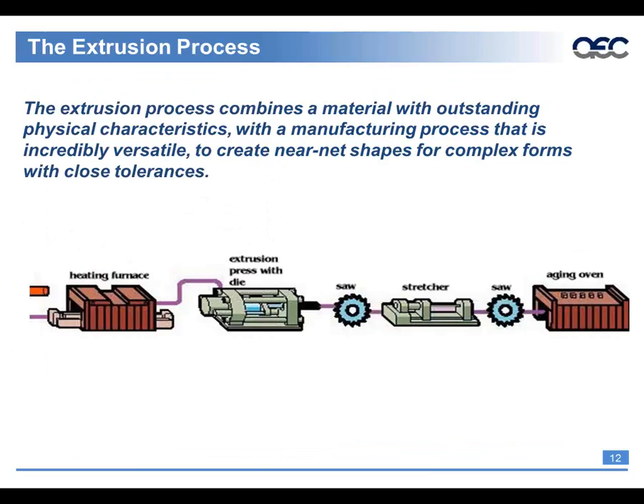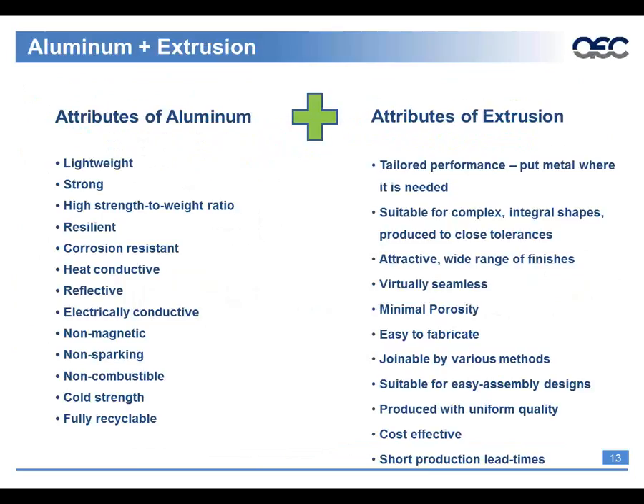The aluminum is then sawed. It's stretched to get back its tolerances and its original shape properties. The aluminum is then cut again to fit in the aging oven, anywhere from 8 to 25, 30 feet. And at that point, it's artificially aged to get back to its original hardness properties. Okay, next slide, please.